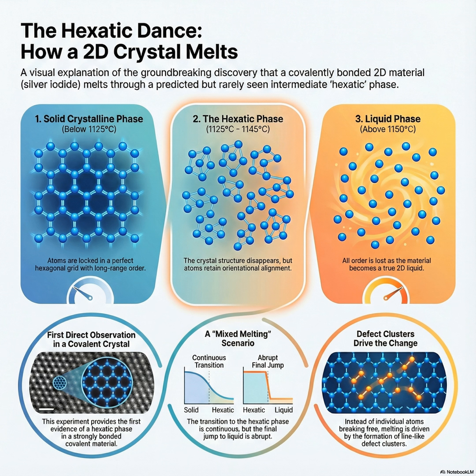Exponential decay. So that's like a cell phone signal just dropping off a cliff the second you pass the tower. That's a great way to think about it. It's a fast drop. It confirms a very short-range structure. It proves that the perfect crystalline rows and columns were quickly scrambled. So translational order was definitely gone, but the second metric, the orientational correlation, that's where the hexatic phase really lives or dies. And this is where it gets really interesting.